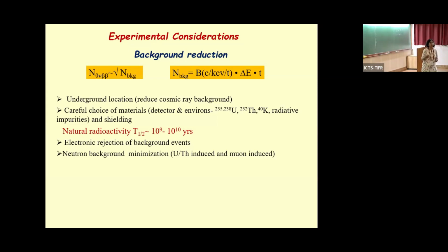And normally those have a very long half-life, like 10^9, 10^10 years. So if I'm doing an accelerator-based experiment, whatever I look at has a much shorter half-life, and they will have much higher count rates. But now you're comparing, when you want to study something which has a 10^24 years half-life or longer, this is much faster. No? So even all the background coming from these less probable events becomes very crucial for you. I'll show you some spectra later: in the natural radioactivity, the highest energy gamma ray which you observe is 2.6 MeV, 2.614.